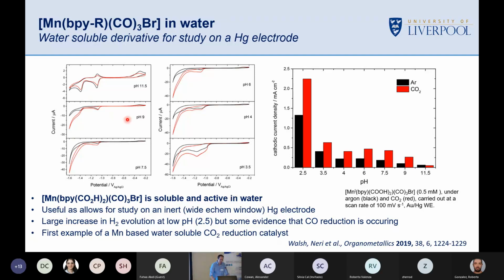And now you can see the behavior. Black is under nitrogen or argon, red is under CO2. And you can see that we see quite a large current enhancement for CO2 reduction at any pH below 9. And actually, we can still see pretty good improvements in current density, and we can see quite a lot of CO produced down to about pH 2.5, pH 3. So this catalyst seems to work reasonably well in moderate acids, not very strong acids.